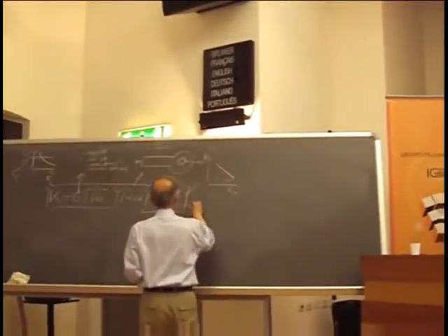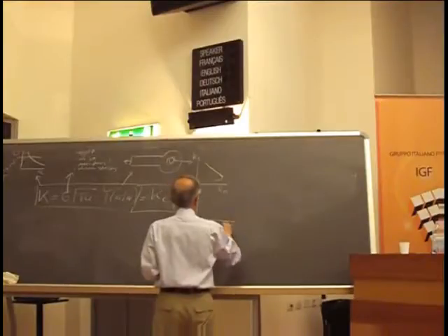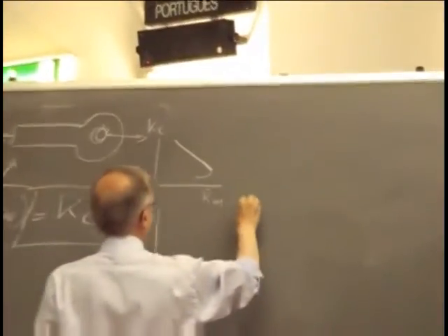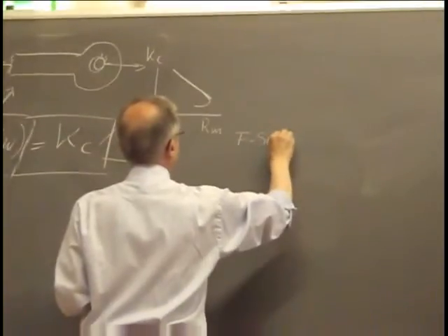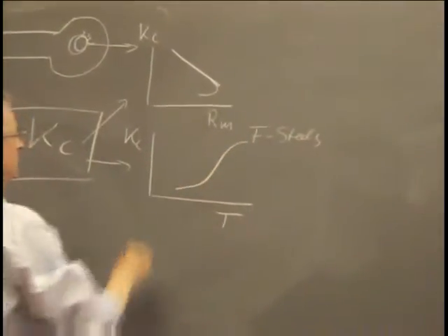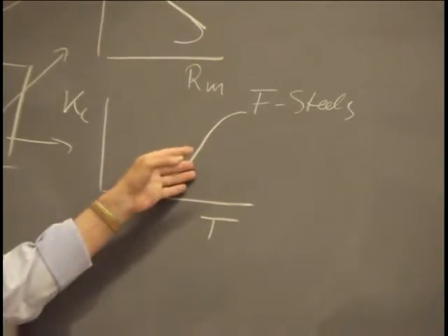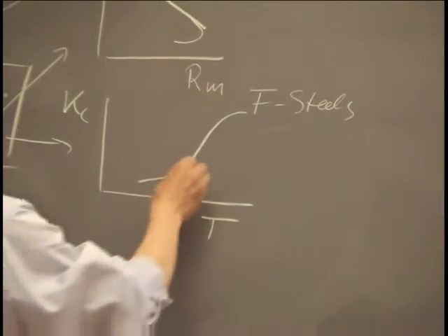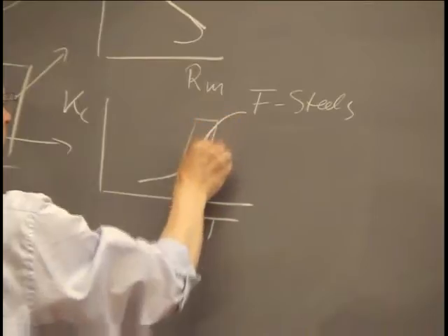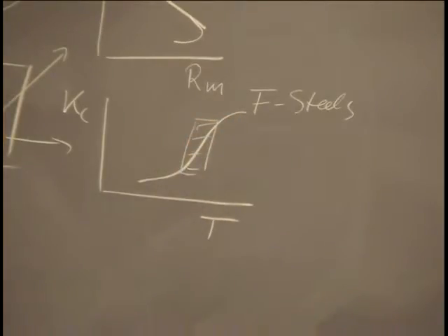Then when we deal with ferritic steels, as a function of temperature, here we have very brittle steels. You get something like this here. We have to take care of the operation temperature. It has to be above the transition temperature. And this is not enough. We have substantial scatter, as I showed you yesterday, by an order of magnitude. And there's no way to avoid statistical treatment of the data and later of the analysis when you go to the structural component.